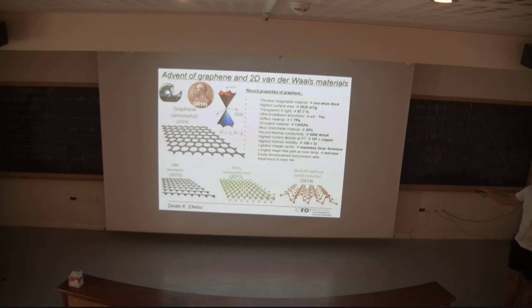For example, these are listed, all the records graphene holds. It's the stiffest material, it's the most stretchable material, it has record thermal conductivity at room temperature, it has the highest current density at room temperature, it has the highest intrinsic mobility at room temperature, etc. Up to this date, those are records which graphene holds.